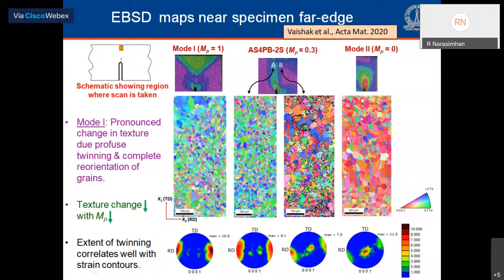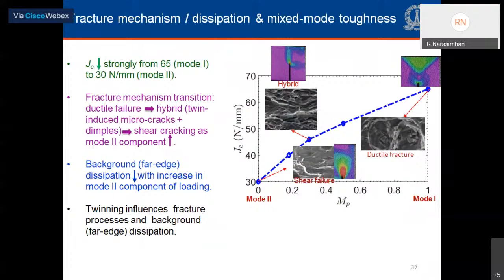Going to the mode 2 case on the right side, extreme image, much less strain at the far field and far fewer twins and far less change in the texture compared to mode 1 or mixed mode case. So with increasing mode 2 component, the texture changes at the far edge of the specimen associated with twinning, as well as the strain concentration at the far edge of the specimen, diminish as you go towards the mode 2 case.